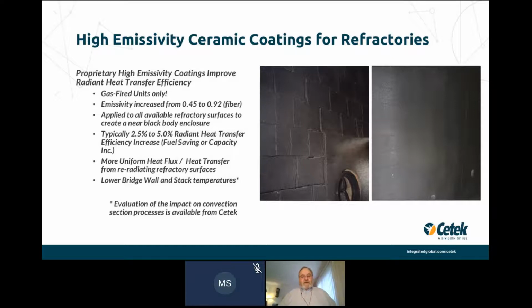Refractory coating pictures tend to be very boring because it's like looking at, like I said, just a black picture. We use these coatings in gas-fired units only, and I'll explain why later on. In ceramic fiber lined units, we increase the emissivity from 0.45 to about 0.92. All of our coatings, tube refractory coatings, which are high emissivity coatings, have an emissivity of 0.92.